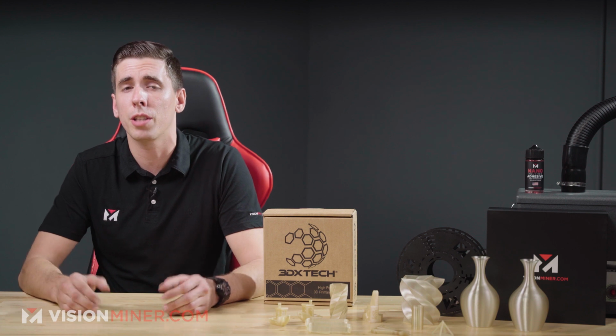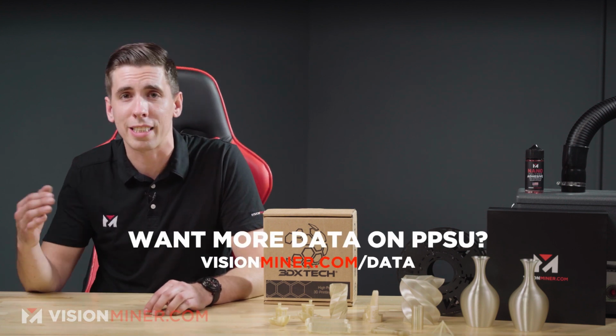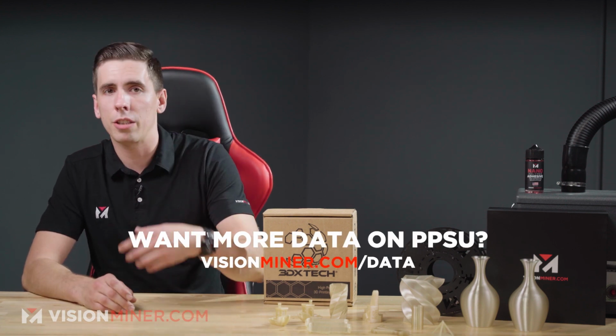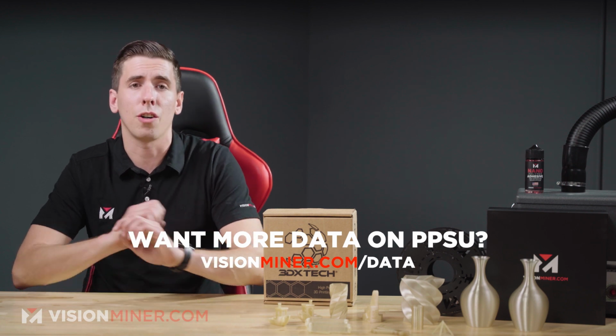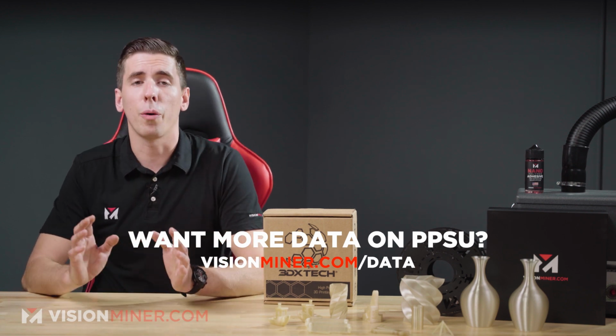And a tensile modulus of around 2310 megapascals. But do keep in mind the way your part's designed and the orientation at which it's printed will have a dramatic effect on the strength, and you'll generally lose a little bit in the z-axis depending how it's printed. All the data sheets are available on our online store at visionminer.com/data, so you can find all the tensile modulus, elongation, impact strength, and all that good jazz on our website.